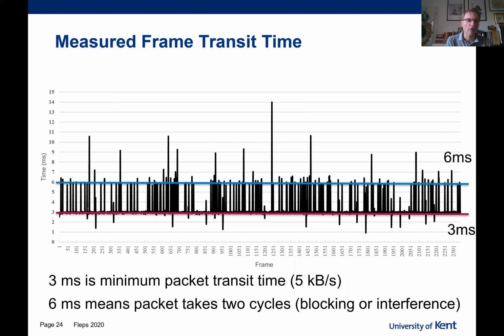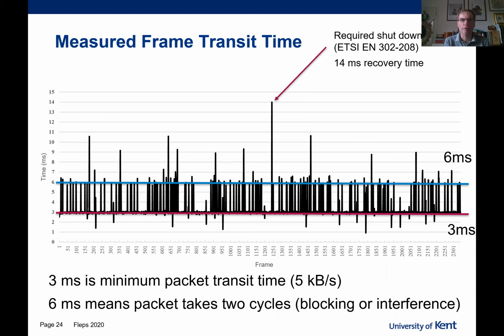And this is caused either by blocking at the tag end to avoid clashes and data loss, or by interference on the RFID link, meaning that packets take longer to arrive and need to be resent. The very long transit time shown in the center of the slide is basically following the regulation required by the ETSI RFID regulation. This says that you can't continuously transmit at the RFID band for more than 4 seconds. So every 4 seconds or so, the system closes down and takes 14 milliseconds to recover. So a packet transmitted at that time will take the full recovery time before it arrives.